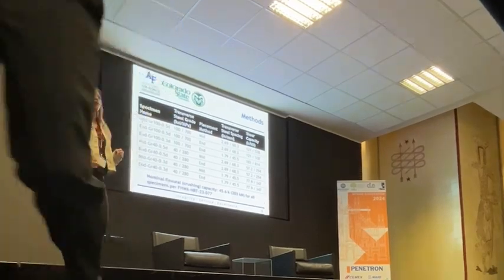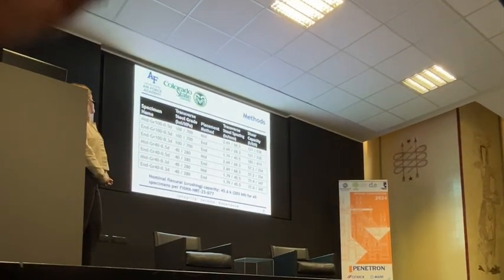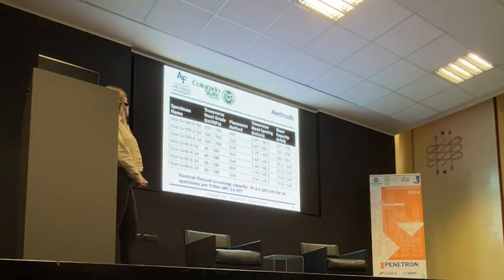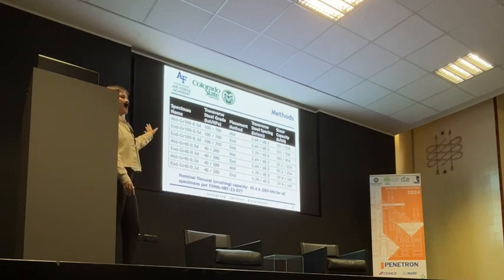Good afternoon. So for our experiment, we cast 7 specimens of the UHPC. They were all short span specimens. You can see here on the left column the specimen names. You read them as such. On the first part, it'll be the placement method, mid or end. The second would be the transverse steel grade, and the final will be the transverse steel spacing.